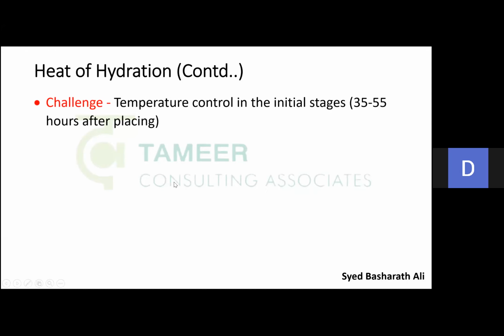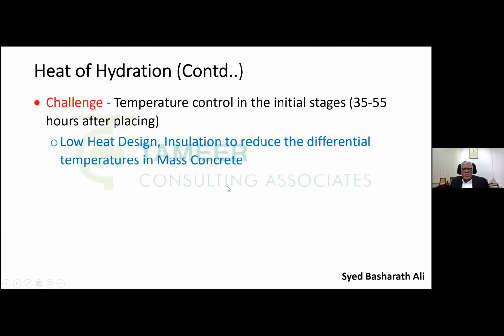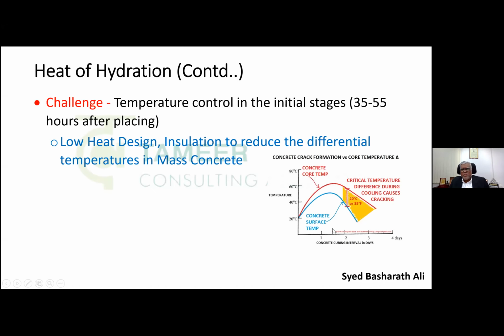Okay. Now, as I said, temperature control in the initial stages, that is 35 to 55 hours after placing, is important. Low heat design and insulation are needed to reduce the differential temperatures in mass concrete. This problem is very acute in mass concrete because the core temperatures will be very high. We either have to measure the temperature at the core and also at the perimeter, or make sure that enough care is taken and the concrete is insulated. This graph shows the variation of temperature between the surface and the core, which could be as high as 22 to 35 degrees centigrade.